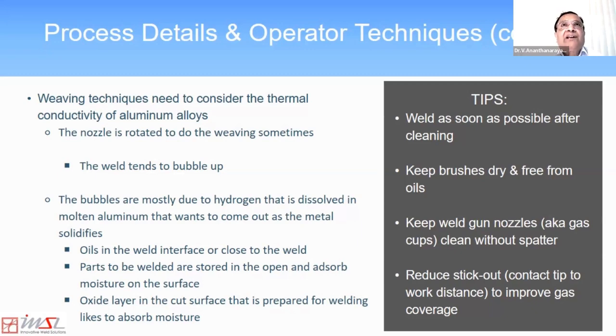The stick out in aluminum welding does not change weld bead profiles as severely as stick outs in steel welding. Because when the stick out in steel or stainless steel welding changes, the heat generated along the wire after it exits the contact tip changes significantly. With aluminum, that heat generation change is not very high, but still it's a good idea to have low stick out so you don't get moisture infringement from outside, and also the shielding gas coverage is good.